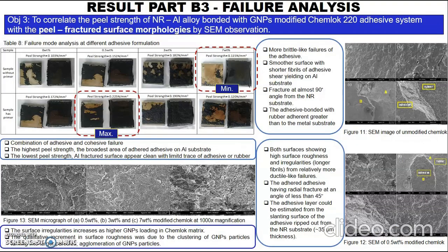And last but not least, the result part B3 is studied to achieve objective 3. Table 8 shows almost all the samples have a combination of cohesive and adhesive failure generally. Then the maximum and minimum peel strength are compared from the aluminum surface. You can see in the maximum peel strength, the aluminum surface has a wide area of adhered adhesive on the aluminum substrate, while the aluminum fractured surface at the minimum peel strength, the lowest peel strength, is almost clean with limited trace of adhesive or rubber.